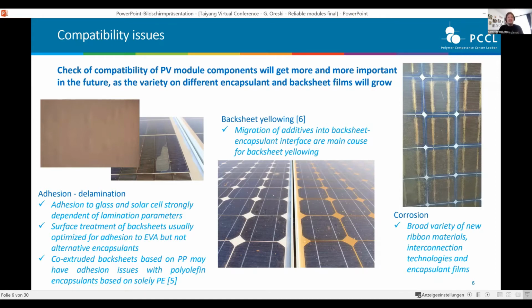The other thing is adhesion, for example, between backsheet and EVA. Let's say back then when just TPT and EVA was there, it was easy. The backsheet manufacturers made some surface treatment of the inner layer, of the cell side layer, and guaranteed adhesion to EVA. However, with these whole new materials, you cannot just optimize it for EVA, because a surface treatment optimized for EVA maybe does not work for a TPO backsheet or for a POE backsheet. So that's the first challenge.